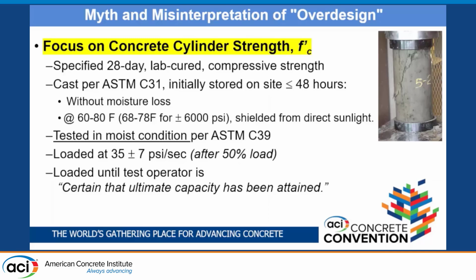Monday morning, the boss says, okay, I need these cylinders broken today, and when you're done, you can clean out the moist room. The test guy's going to say, I got to figure out a way to make this last all day long, and we very slowly load, and the strength is going to go down, okay? And they have to be loaded until the test operator is, quote, certain that ultimate capacity has been attained. Now, the problem with testing all the way to ultimate capacity is you got a lot of fragments and parts and pieces and dust that you have to sweep up. So if you just load them until they start saying, ouch, ouch, stop the machine right there, you'll get a low break, but the cleanup is a lot easier. So exactly as the prophets foretold, the testing has got to be good.